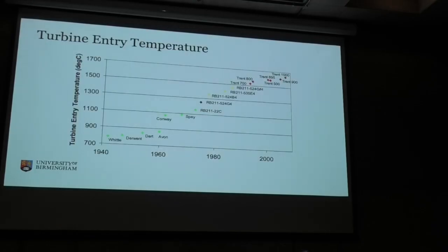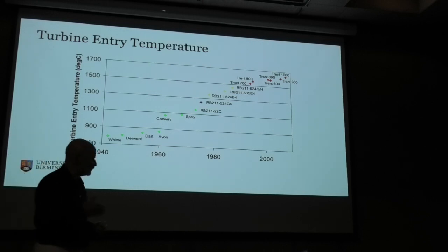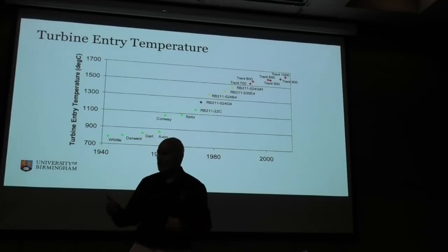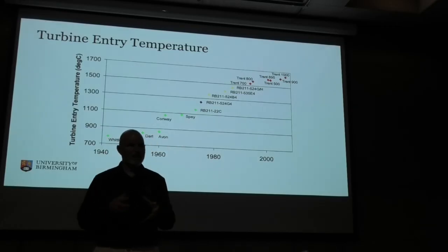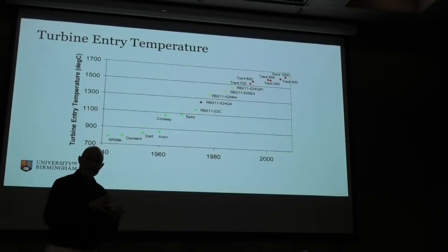And what we've done over the years, we've just driven that temperature up. We would like it to get to about 2,200 degrees C, maybe a bit more, and then burn the fuel as hot as we can to make it as efficient as we can as a thermal engine. 2,200 degrees C will melt most things. There aren't many things around that you'd want to make a turbine out of that will survive that. So currently we're up at just over 1,600 degrees C.